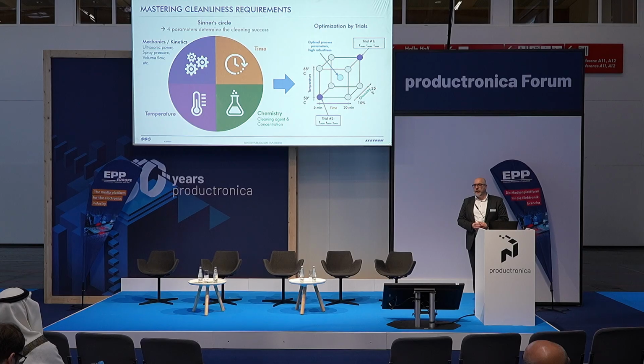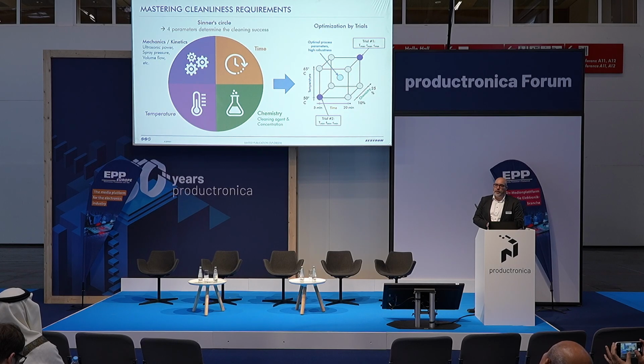Yeah, so how to find out the optimal process? Typically, this is done by trials, of course, with some pre-knowledge, let's say. So, for instance, at our site in Ingolstadt, or close to Ingolstadt, we have a big technical center with different machines where we can do cleaning trials with our chemistry for customer boards. And we also have big databases, for instance, of solder pastes and other materials, also coating materials. So we know already from experience which processes are typically working together with which challenge.